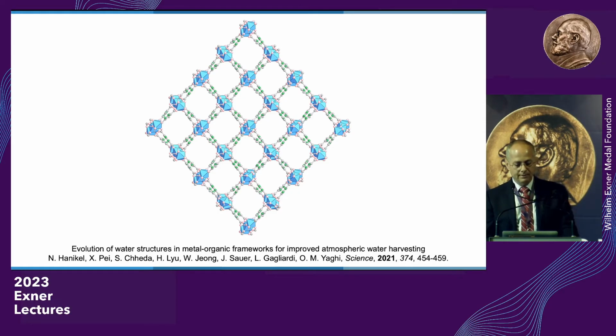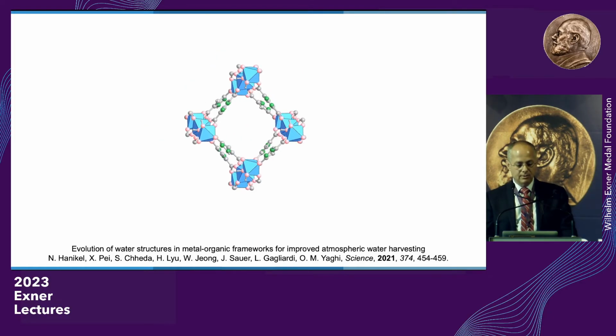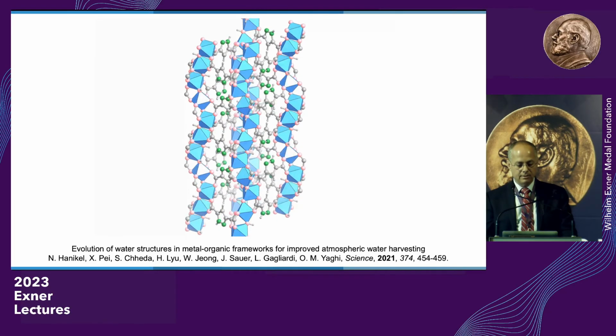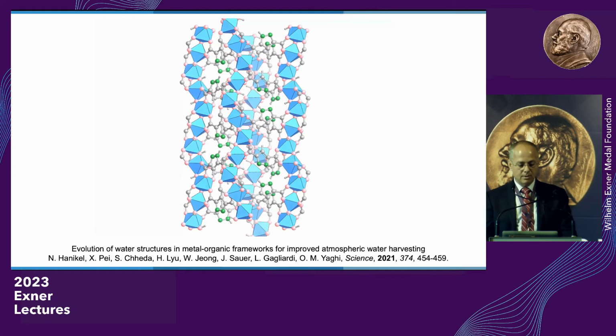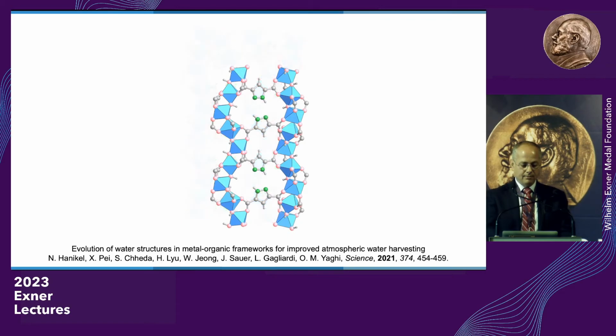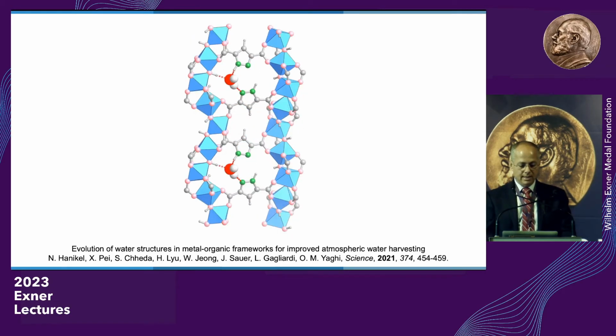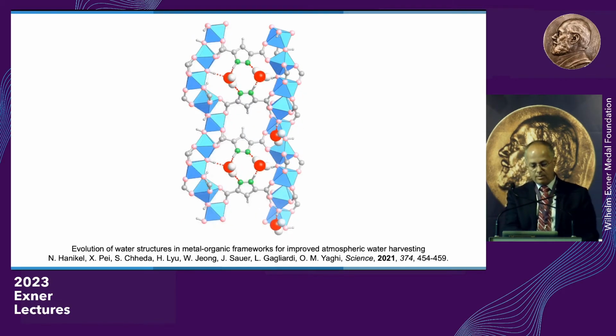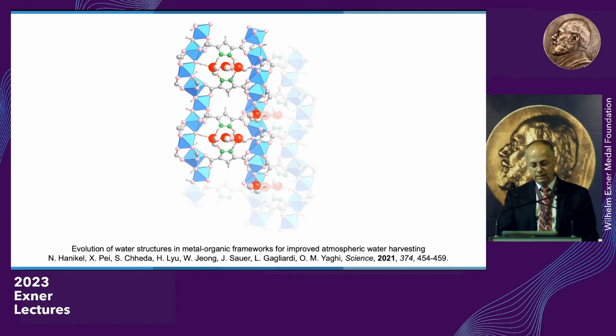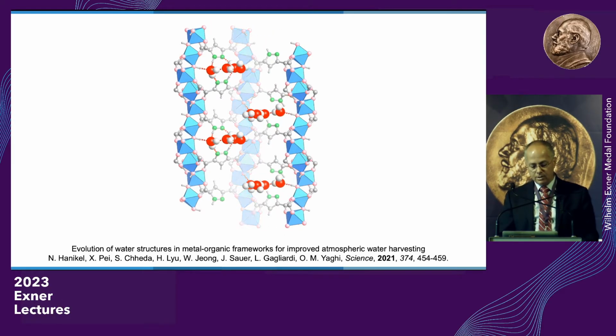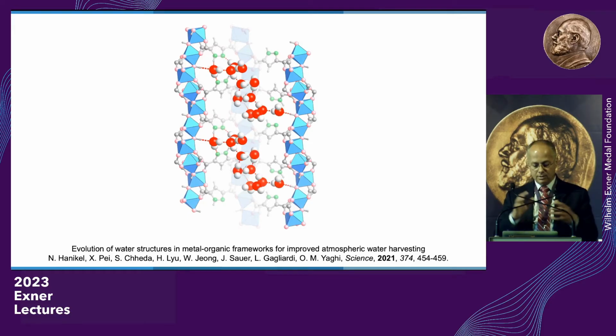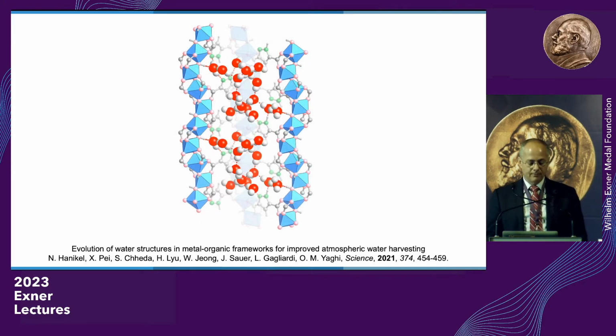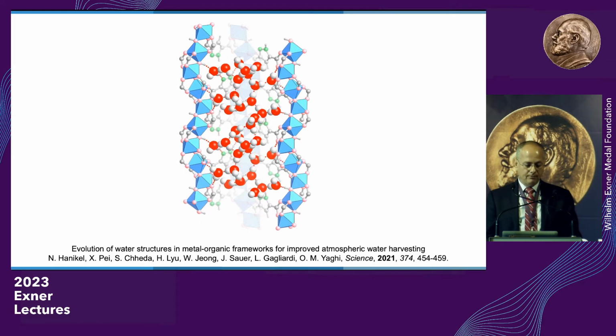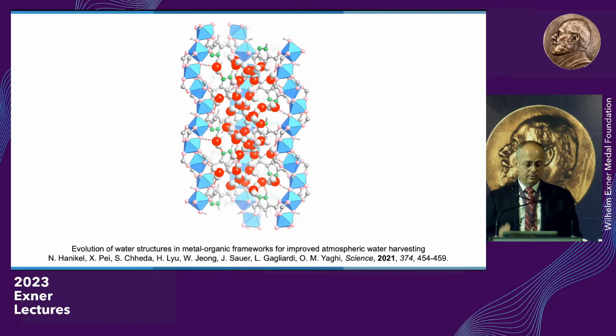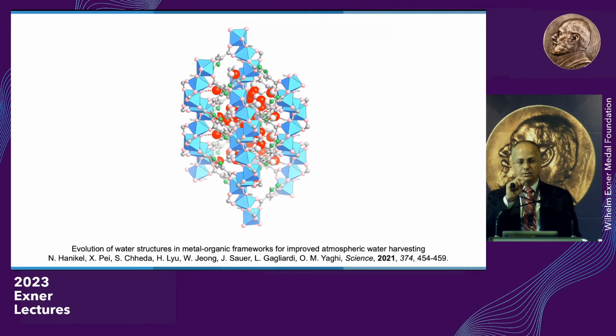So here's the pore. You'll see the hydrophilic regions have the nitrogens in green, hydrogen bond donor and acceptor. This is the first water molecule. There's another position on the blue metal oxide region. Now you see extra water molecules are bridging over the hydrophobic regions here before the structure is completely filled with water.